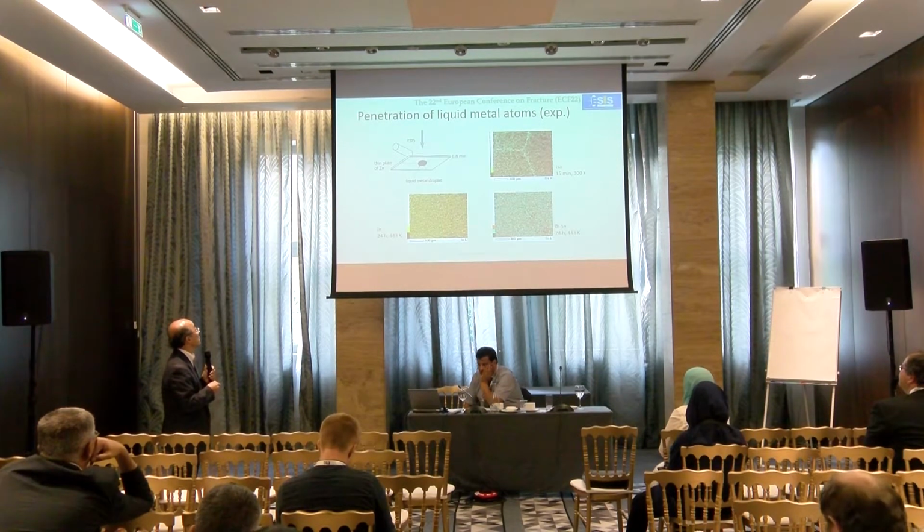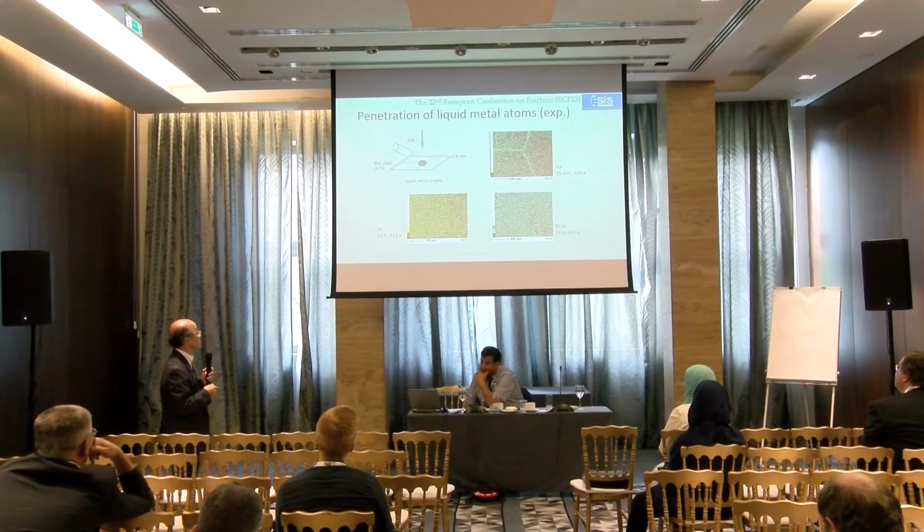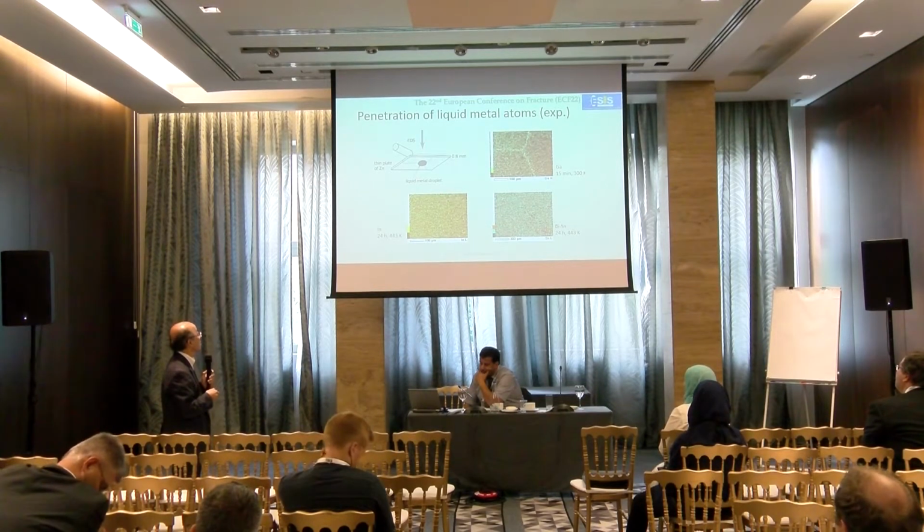A thin plate of zinc was prepared after etching to reveal the grain boundaries. A small drop of liquid metal was placed on the grain boundary and kept above the melting temperature of the liquid metal, and observed from the opposite side of the droplet.